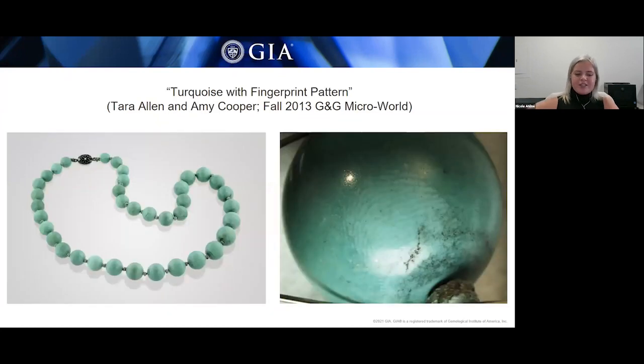So this next piece serves as a useful example of why turquoise is routinely treated. Examined at the Carlsbad laboratory was this natural untreated bluish green turquoise bead necklace. During examination, some beads showed a discoloration pattern that resembled fingerprints. And you can see it in the photomicrograph on the right. The beads had an RI of 1.6 and no polymer related peaks in the infrared spectrum, which ruled out the turquoise beads being polymer impregnated.